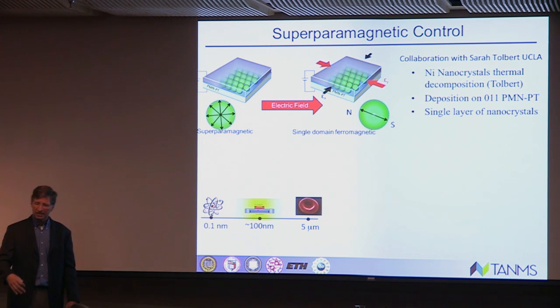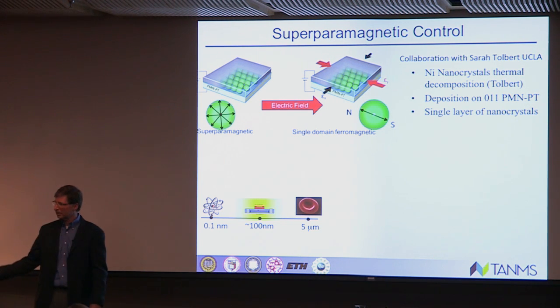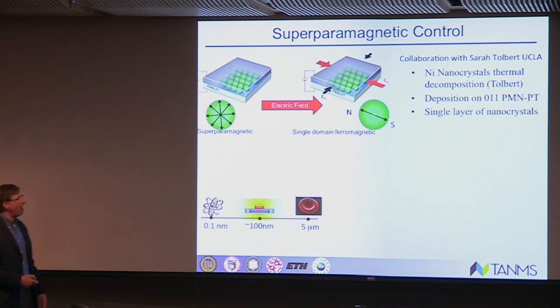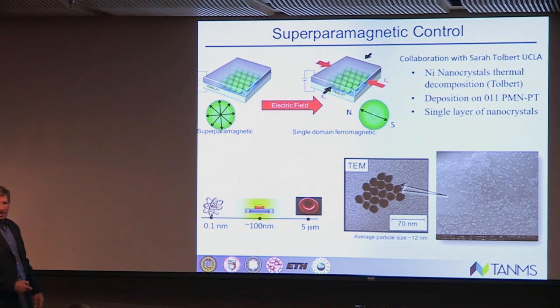So I was talking to Sarah Tolbert over in chemistry. She goes, oh, that's easy, we can do that. And Laura sitting in the audience says, oh, I can do this. I think after a couple of weeks using thermal decomposition, she was able to make these nickel nanocrystals. How big? About 10 nanometers. Her working with Hyung Suk were able to put those down on our PMN-PT surface.